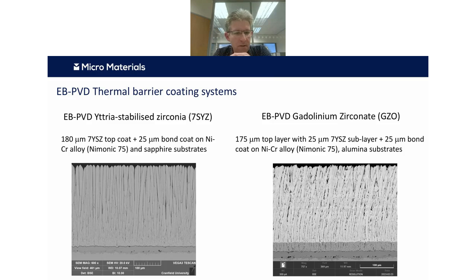So the two thermal barrier systems that we're going to look at today are an E-beam PVD yttria stabilized zirconia system, 7YSZ, and that essentially is a ceramic top coat with a thinner bond coat, and it's on either Nimonic 75 or sapphire substrates, and a similar thickness gadolinium zirconate system, and in this case it's effectively a bi-layer system with a gadolinium zirconate top layer and then a 7YSZ sublayer, and again the same bond layer and similar substrates.